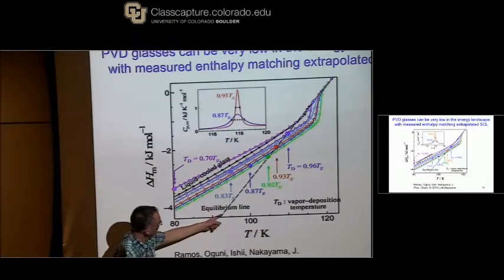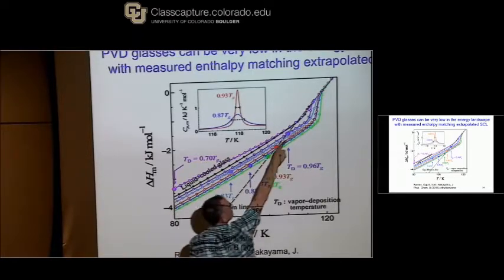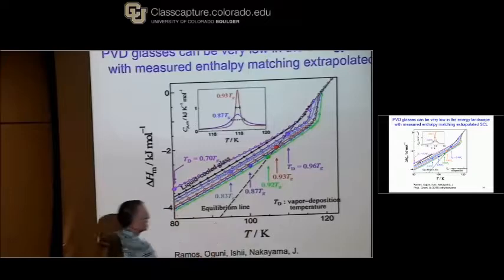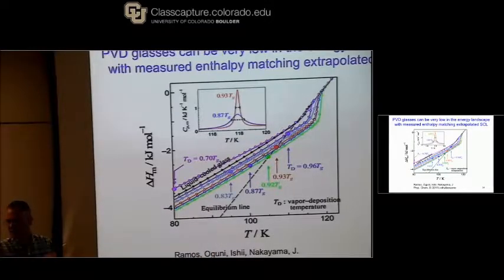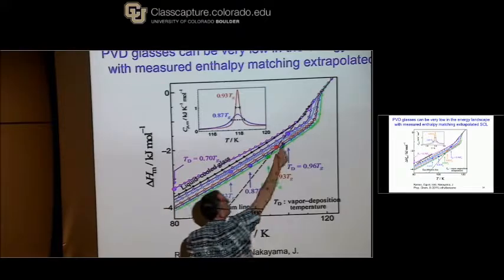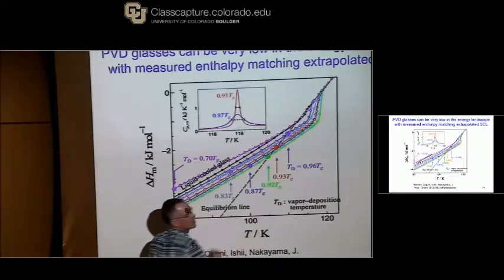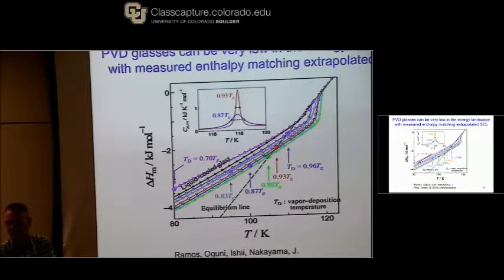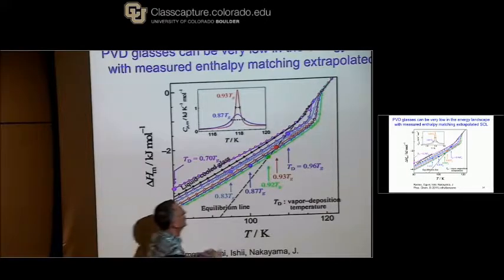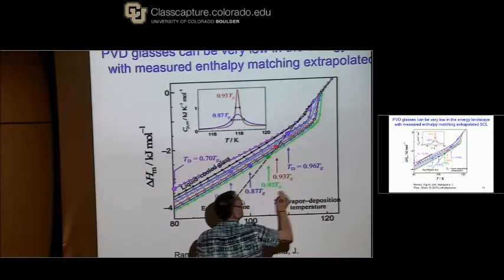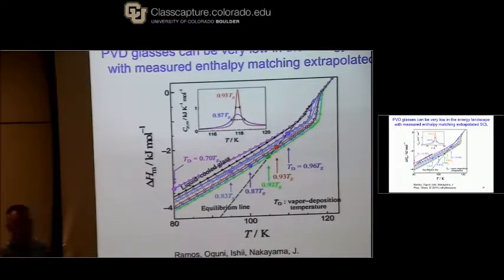So now this dotted line is really important. Way up there someplace is the supercooled liquid. If I extrapolate the behavior of the supercooled liquid, that's the dotted line. Now, just pay attention to the points. These are the enthalpies of the as-deposited glasses, okay, plotted at the temperature where they were made. Okay? And so what this says is that if you deposit at any temperature at 0.92 TG or above, the material that you make, just as deposited, has the enthalpy expected for the equilibrium supercooled liquid. Okay? So this is exactly analogous to the story I just told you about the density.